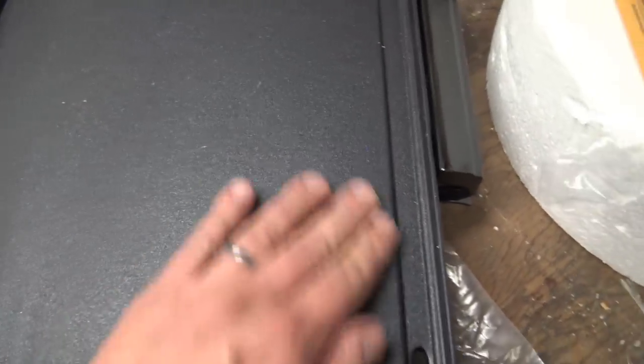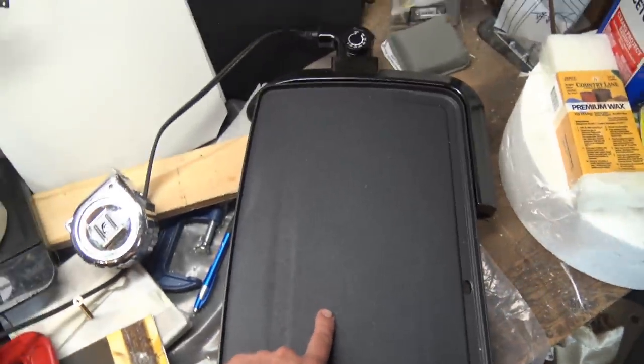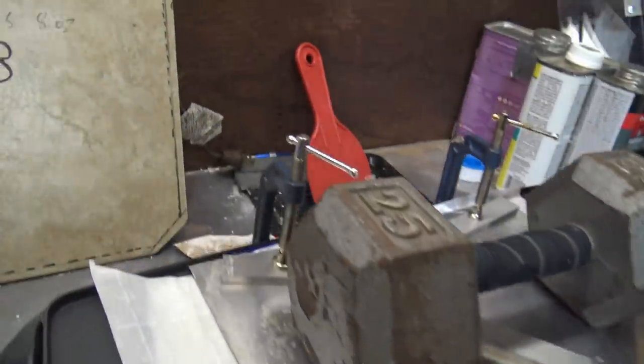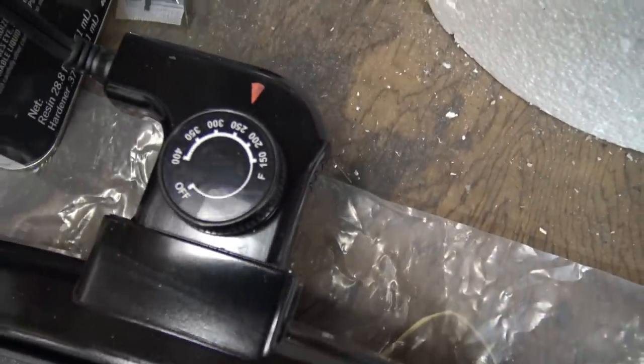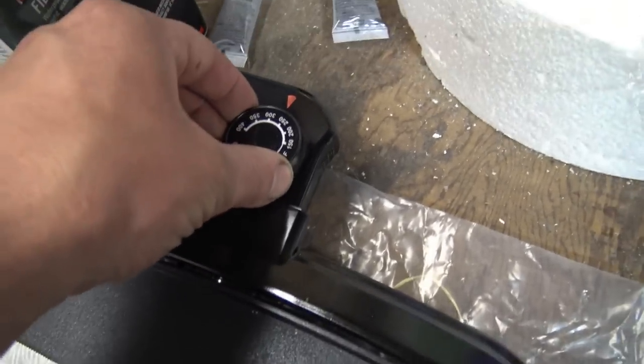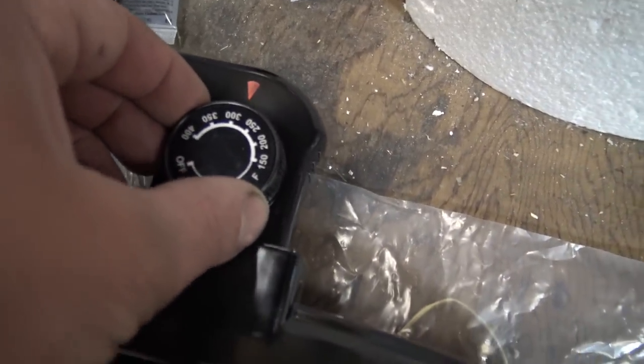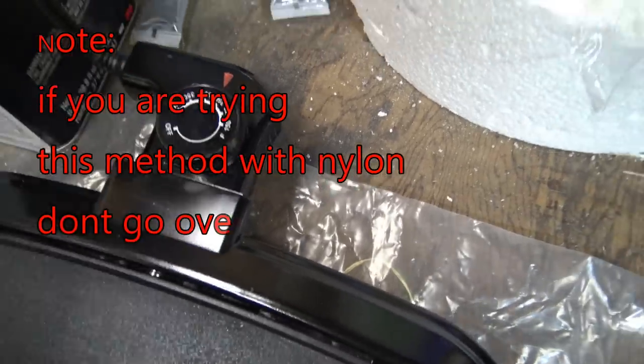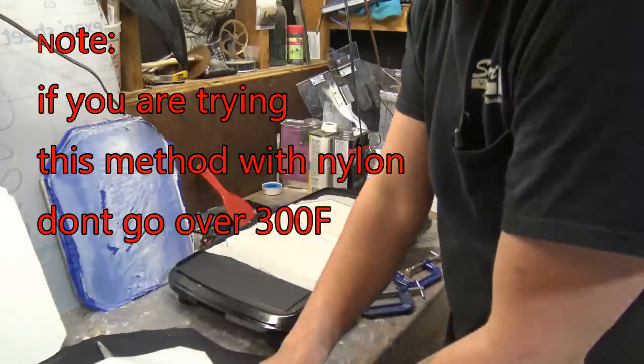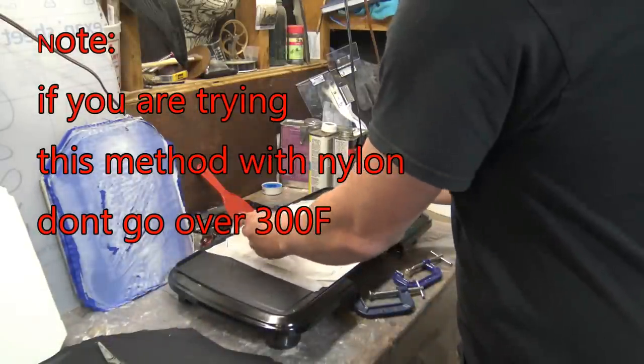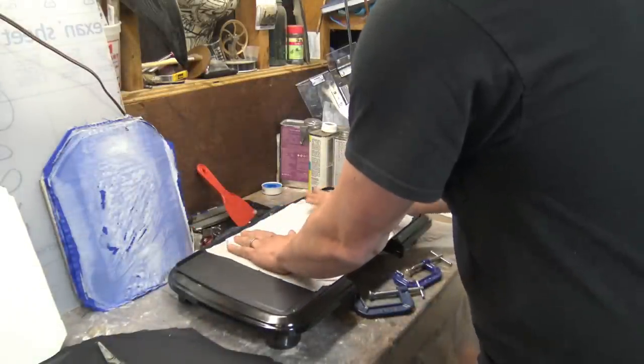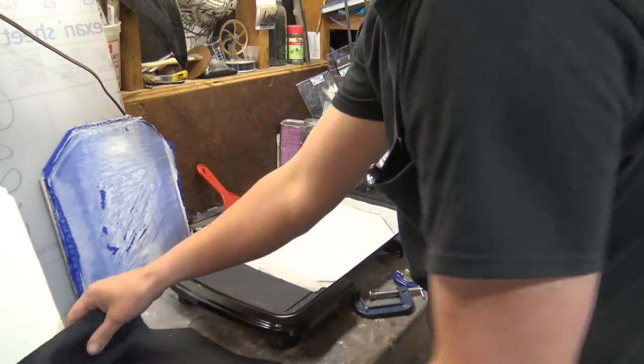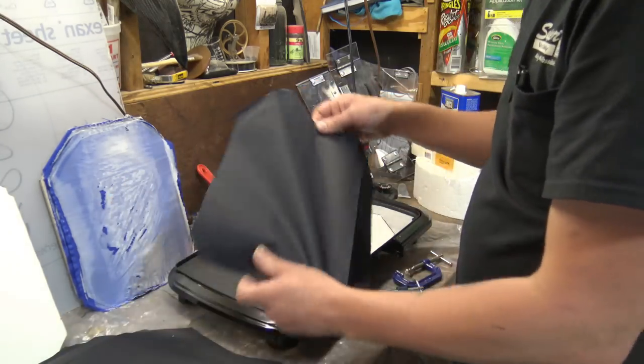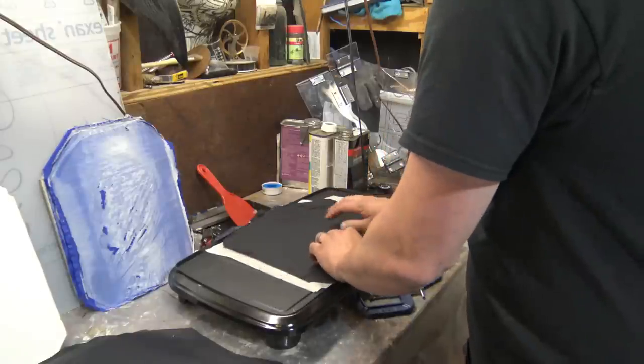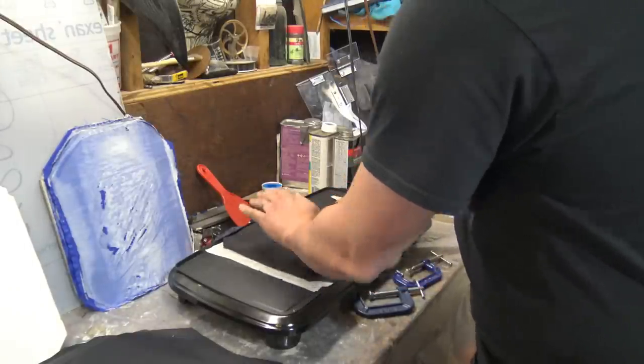So for my very first experiment, I used 3 to 5 layers of nylon, and I set it to 350 degrees Fahrenheit, much like I would with the oven. This ended up being way too hot, as it damaged the nylon. So I backed it back down to 275 degrees to 300 degrees Fahrenheit and found that that was a perfect range. So for pressure, I used 4 clamps, a sheet of metal, and a 25-pound weight. I would also use parchment paper to keep the high-density polyethylene from sticking to the surface of the metal. Once I had a method that worked down, I made 5-layer plies to see how well it was holding together.